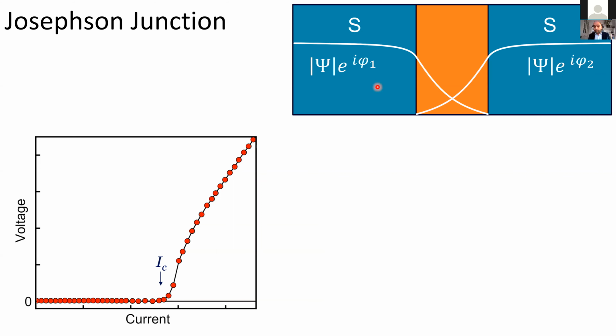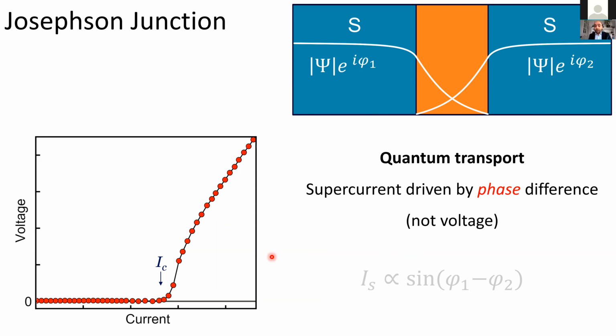And the answer, of course, is not voltage, because as you can see, the voltage is zero. No, the supercurrent is driven by the phases of the two superconducting wave functions. And that's described by the Josephson relation. But the phase here plays a very important role, because it adds a sort of wave-like characteristic to your electrical transport, which, in a way, you could say is similar to light.